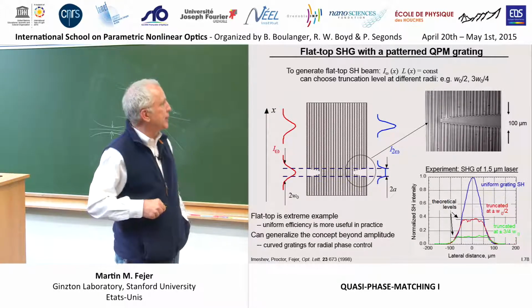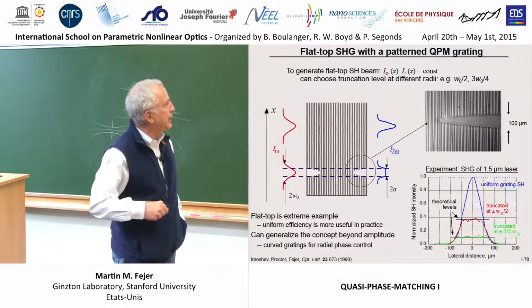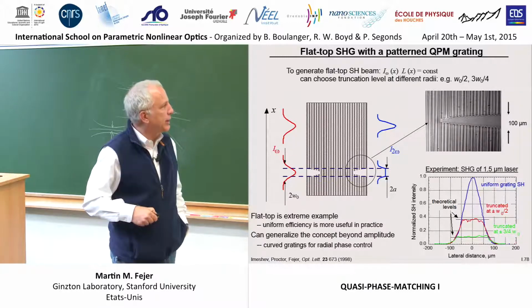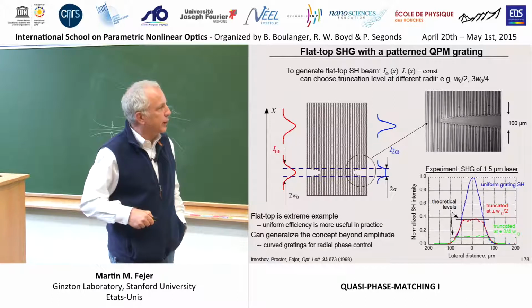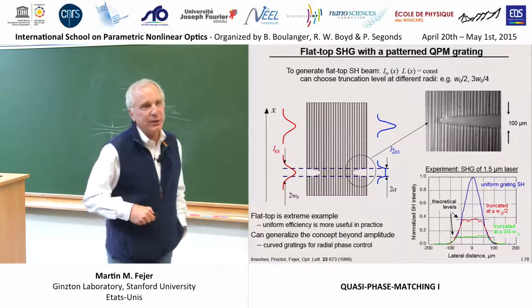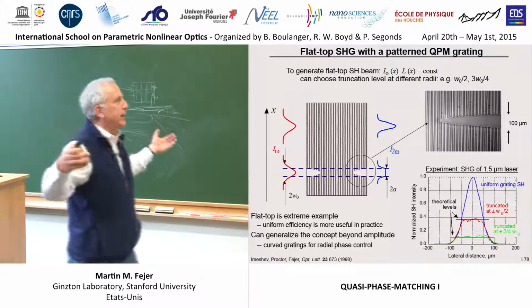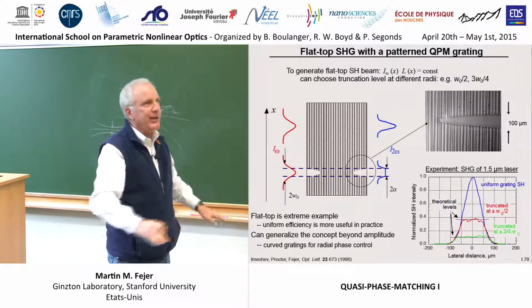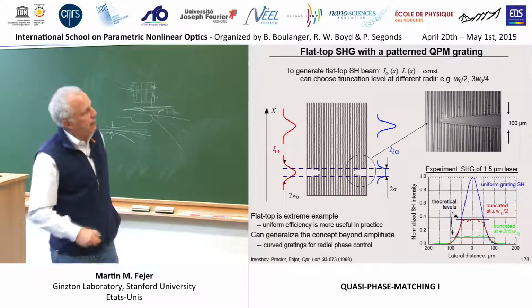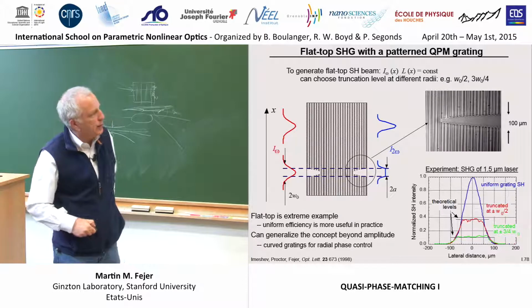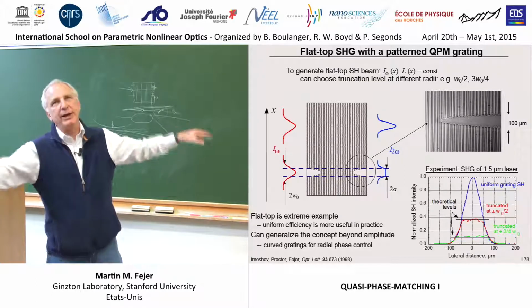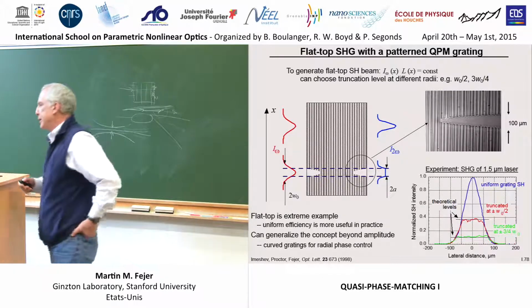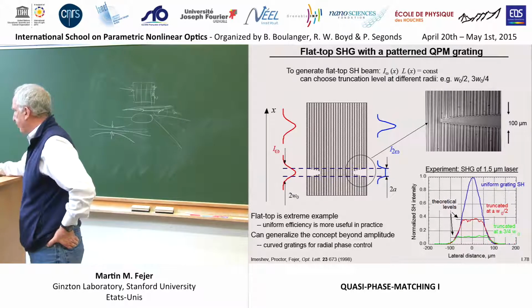So in other words, the product of the intensity and the length squared here was conserved over a large portion of the Gaussian. So this would not fix your time domain pulsing. I mean, you're still going to have a temporal peak if you have a pulse, but you can certainly reduce the amount of radial variation in the mixing efficiency by using such a structure.